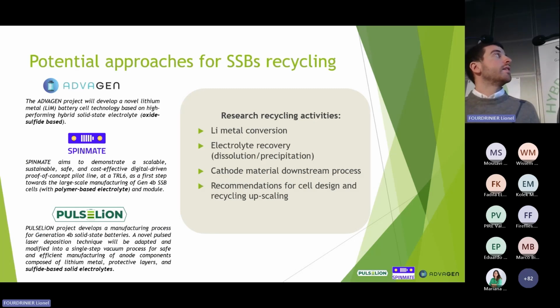So in these three projects, ADVAGEN, SpinMate, and Pulse Lion, we are working on the recycling task of the projects. We have different chemistries in the electrolyte of the three projects. In ADVAGEN, we have oxide sulfide electrolyte. In SpinMate, we have polymer electrolyte, and in Pulse Lion, we have sulfide electrolyte. In the three of them, we have the lithium metal as anode. And well, the research activities that we have in these projects are related to the conversion of the lithium metal, the recovery of the electrolyte by the solution precipitation approaches, the downstream process for the recovery of the cathode materials, and then recommendations for the cell design and the upscaling of the recycling.